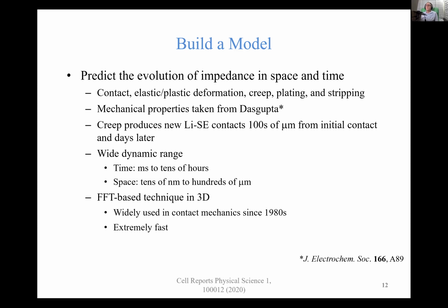Creep is really important. Creep is what happens if you push on a material below the yield strength and you get permanent deformation, nevertheless. And lithium creeps. So you push on it even relatively gently, and it's gradually going to flow. And this flow can move over large distances, in our case, let's say hundreds of microns from where you initially contact. And the creep just continues. There's nothing to stop it. And so it can go on for days, for example.